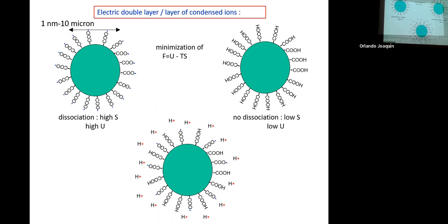Of course, you want to minimize the free energy, the Helmholtz free energy, by minimizing the internal energy and maximizing the entropy. So there are two implications. One is that all the groups dissociate and the H+ vanishes to infinity - this makes the internal energy of that state very large, because you have to separate the positive charge from the negative charge. But it makes the entropy high, because the ion can probe the entire volume. So the internal energy is high, which is unfavorable, but the entropy is high too, and there's always a trade-off between the two.